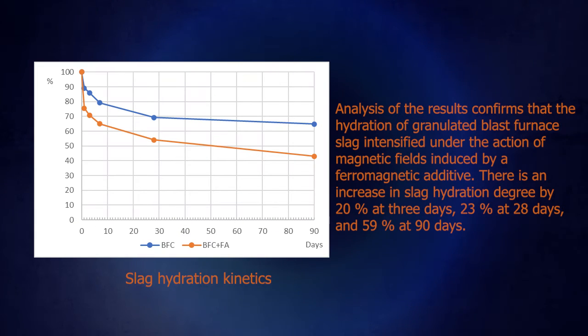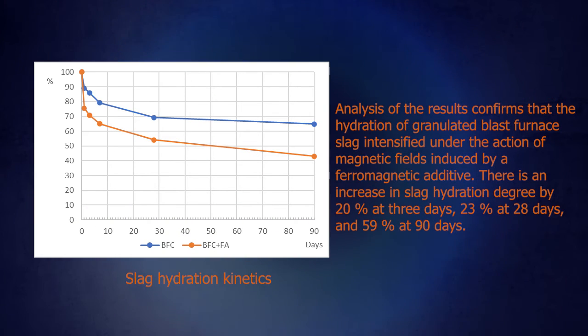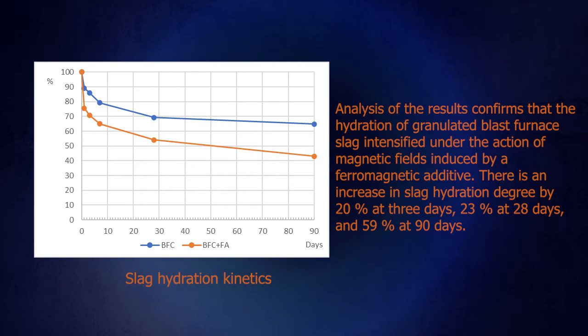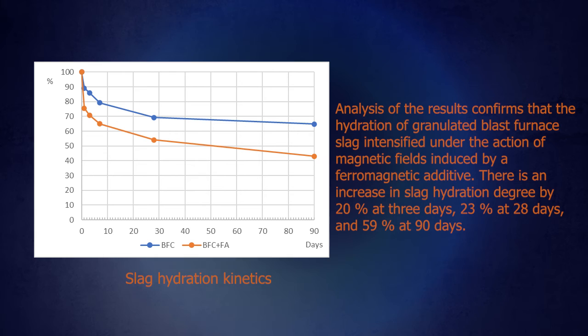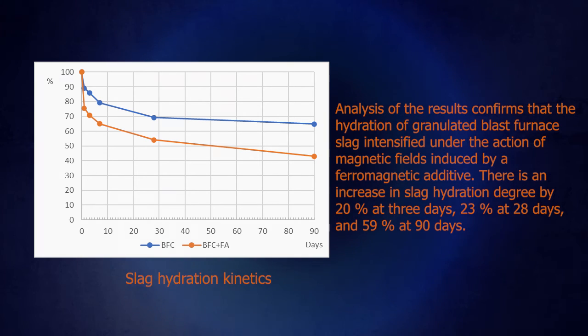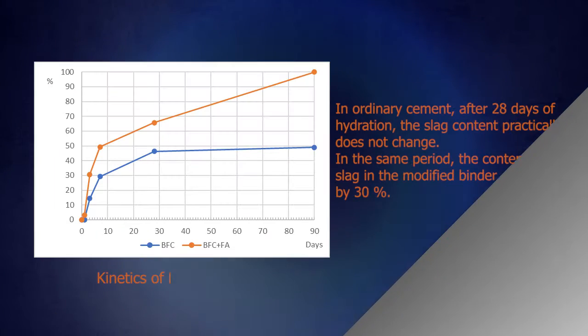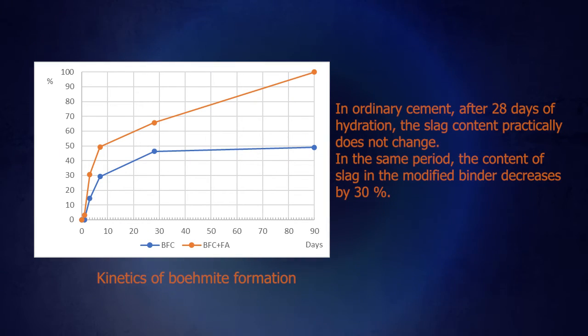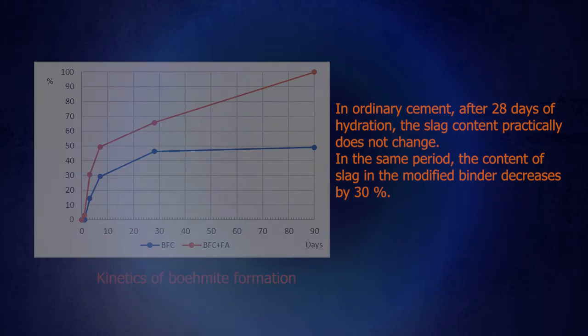Analysis of the result confirms that the hydration of granulated blast furnace slag intensified under the action of magnetic fields induced by a ferromagnetic additive. There is an increase in slag hydration degree by 20% in 3 days, 23% at 28 days, and 59% at 90 days. In ordinary cement, after 28 days of hydration, the slag content practically doesn't change. In the same period, the content of slag in the modified binder decreases by 30%.